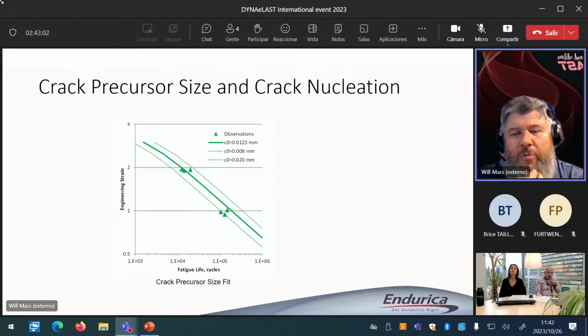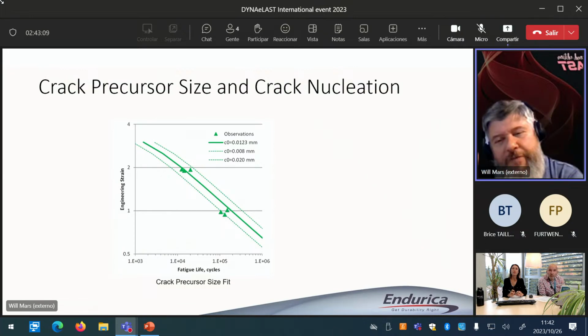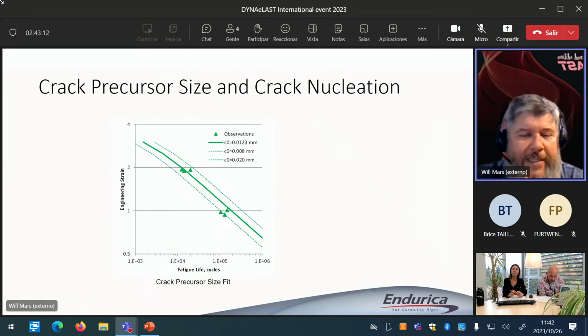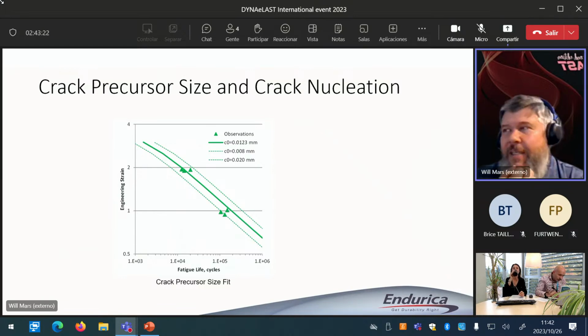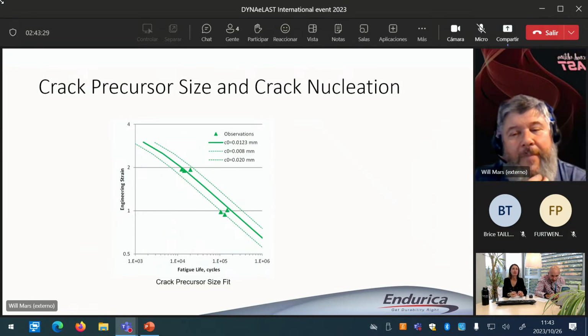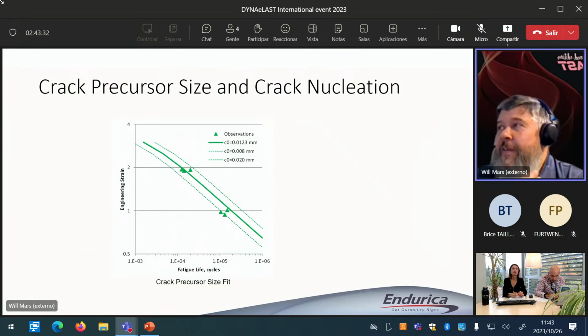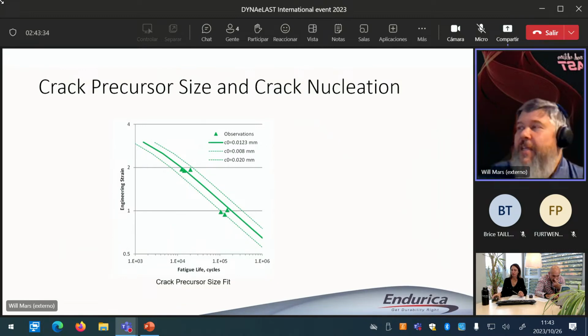As you change the precursor size, those theoretical curves will shift to the right or to the left. And the way we identify the crack precursor size for the material is by choosing the precursor size that lines up the calculated curve from the crack growth rate law with the observed crack nucleation data. In this case, that gives us a crack precursor size of about 12 microns.